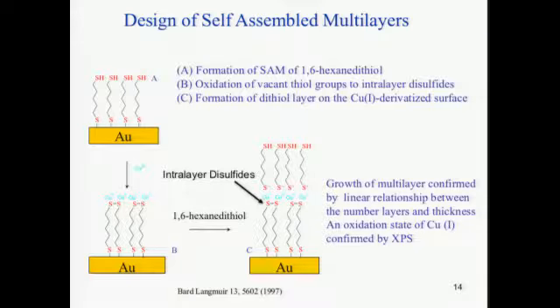And the point here was that if you took one dithiol, you introduced it to a copper with the +1 oxidation state, it would coordinate with the two thiols and make a bond, make an alkane thiol. This is what this is called, alkane thiol, with sulfur connected to a copper, connected to another sulfur, and so forth. And one of the ways we figured out whether this would work or not work is to look at the oxidation state of copper. Because if copper is in the proper oxidation state, we can determine its coordination with the sulfurs.